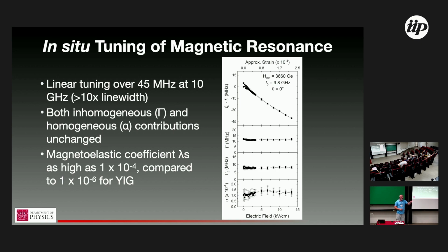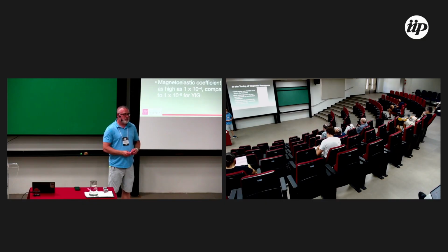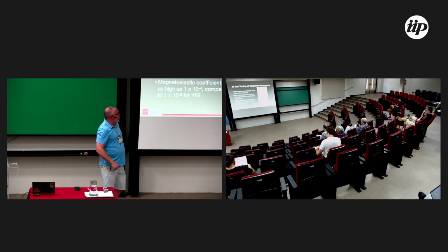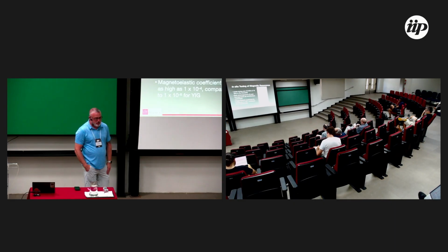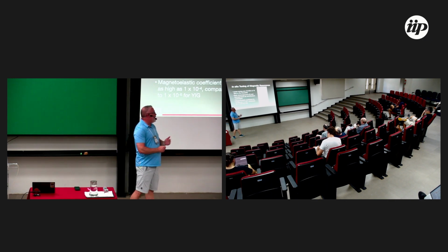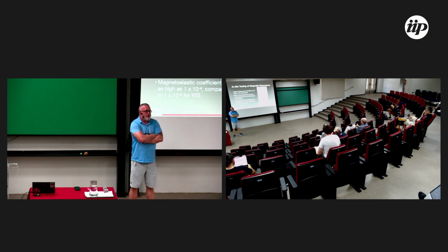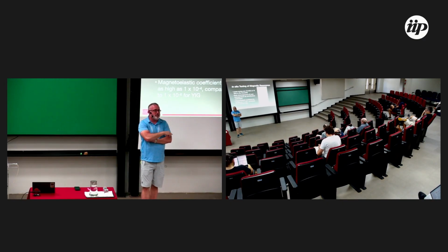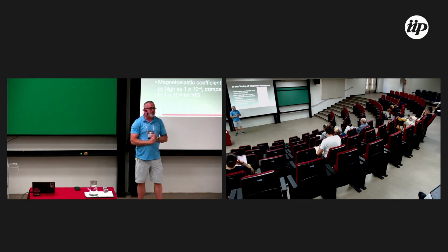I think Georg has a question. Yeah, just, I mean, you showed that you can shift the resonance frequency by applying strain, but on the other hand, when cooling down, you basically changed the anisotropy. So is this directly related, or did you check whether you have a change in anisotropy there? Certainly you would observe it as a shift, but did you check also the perpendicular and in-plane shift? Yes, I didn't clip out that from the paper, but we do the full angle dependence and fit to extract 4 pi Ms and get comparable numbers.